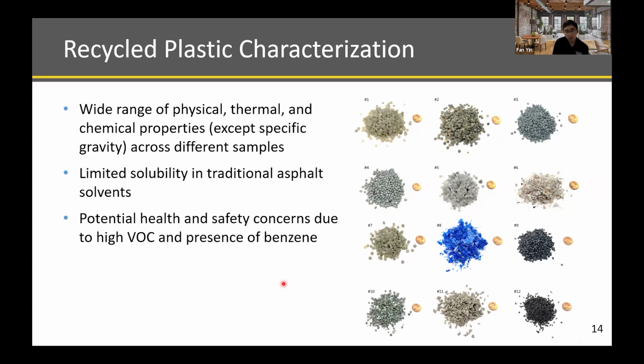Another important finding is that a couple of the samples that we tested surprised us. They have some potential health and safety concerns, because when we look into the GCMS analysis, they have high volatile organic content. And also one of the samples even has the presence of benzene. That's definitely something that we don't want to work with, not only in the lab, but also at the plant. So just be mindful about that. Depending on where those materials come from, they could have these issues, and that's definitely something that needs to be addressed moving forward.